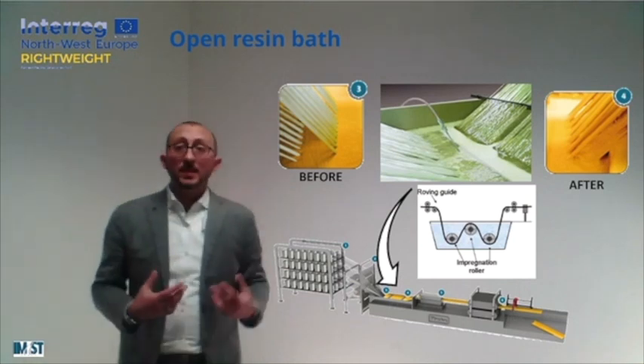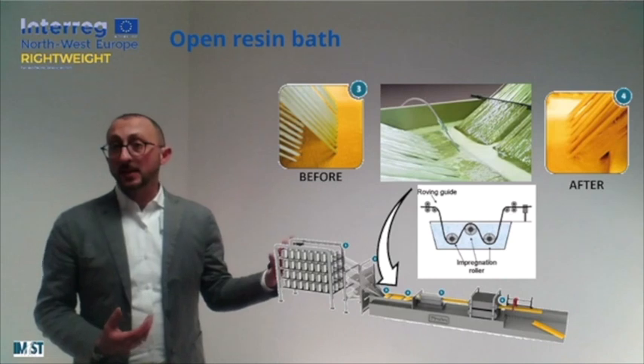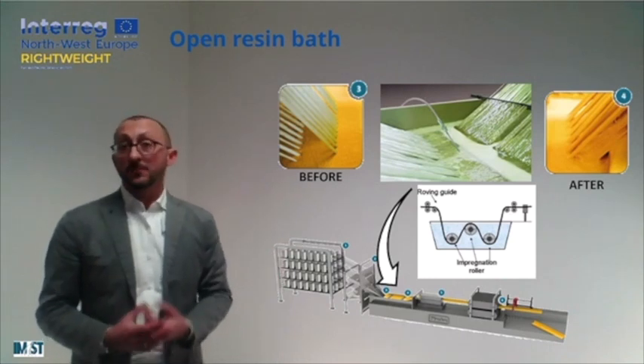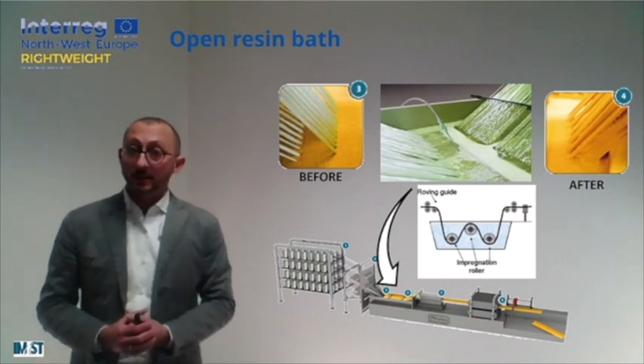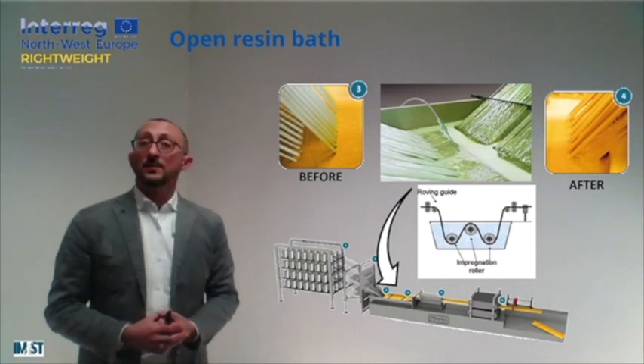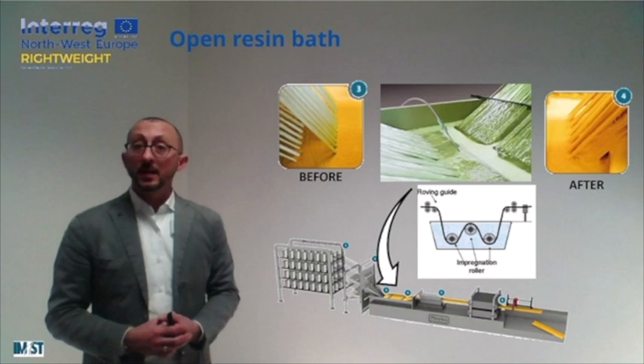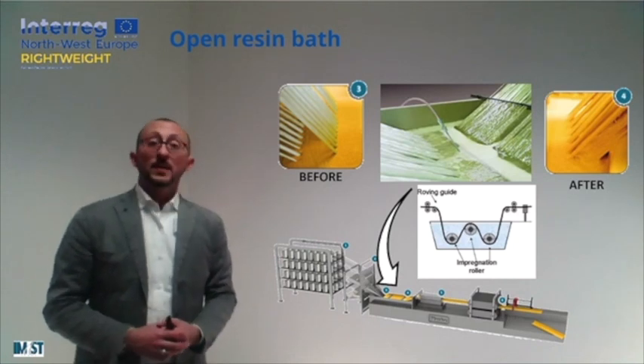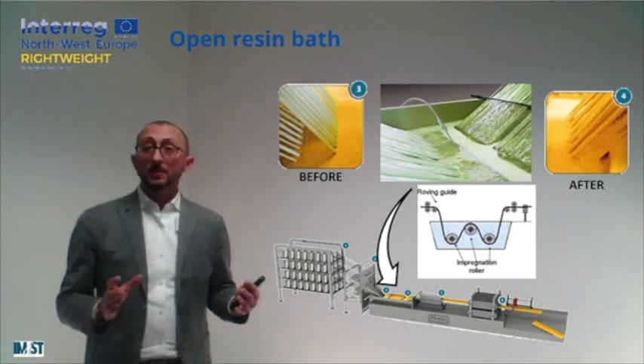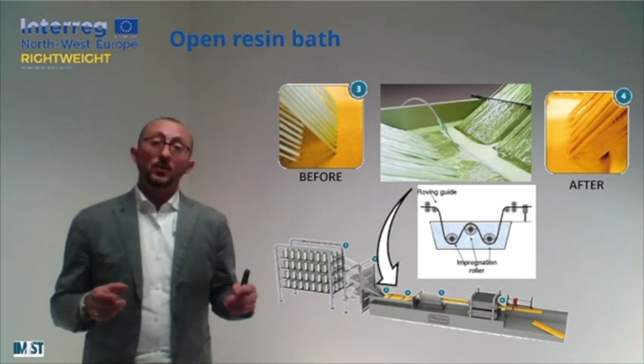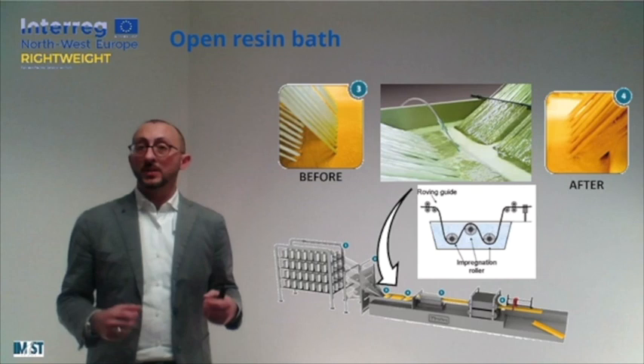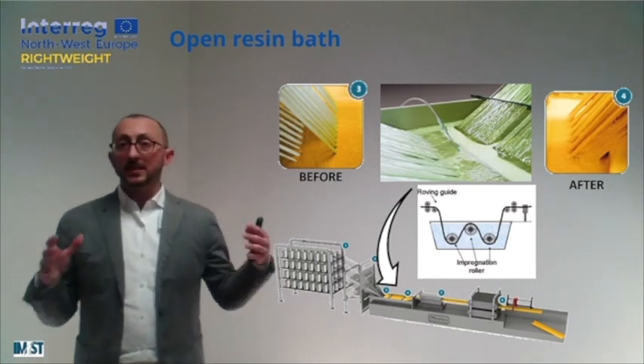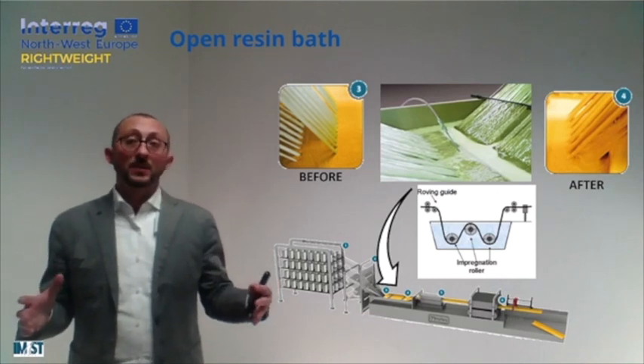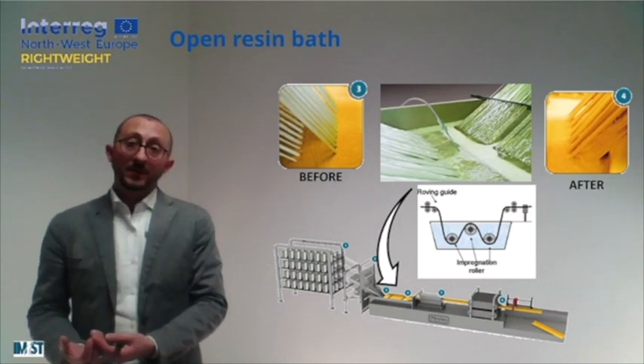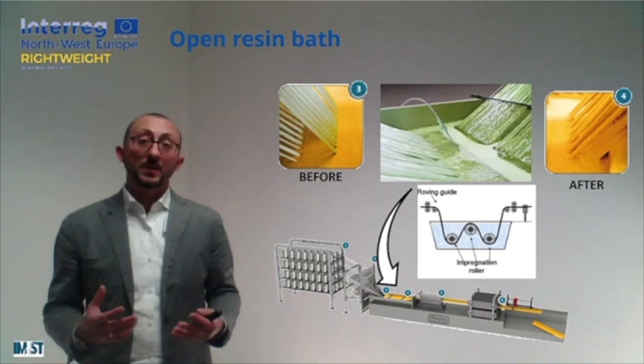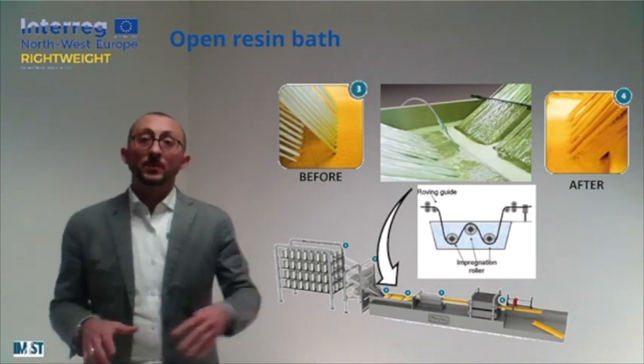Of course, considering some limitations in terms of viscosity, this technique is particularly suitable for, if not limited to, thermoset resins. In the case of thermoplastic resins, the viscosity of the material is typically too high in order to have the same results. The temperature of the resin inside the open bath is obviously monitored in order to be sure that no reaction is taking place. Because, of course, considering that inside the resin bath we have a really high amount of resin, if any kind of reaction starts there, we will not be able to stop it. And once again, we will have some problems with our process.